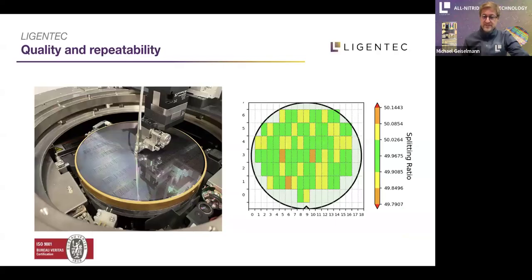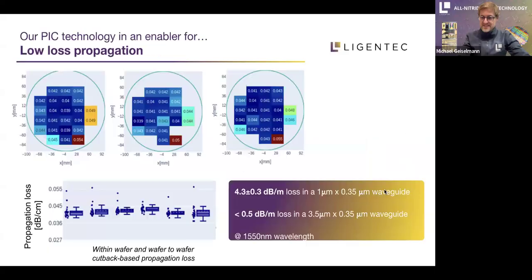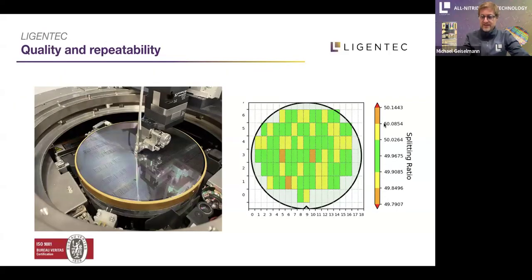So we have here an MMI which was designed to have a 50-50 splitting ratio. And if you look at the splitting ratio that is shown here on the color scale, we are tracking a splitting ratio from 49.79 to 50.14. And these are kind of the outliers, and we have a very good performance across the whole wafer of almost perfect 50-50.0 splitting ratio.